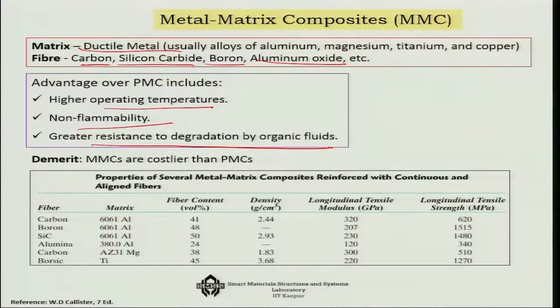In fact some of the MMCs, like carbon with aluminum as matrix, you can see you can get a very high tensile modulus, something like 320, and the strength is something like 620. So this is very high considering the density is only 2.44. Similarly, if you look at all of them, you will get an idea of where exactly we are in terms of the metal matrix composites, and in almost all the cases it is much better than the